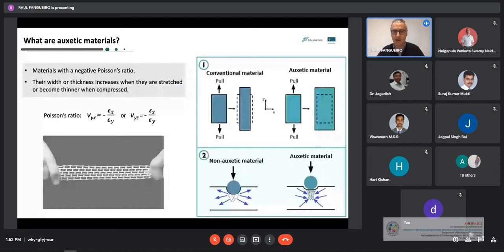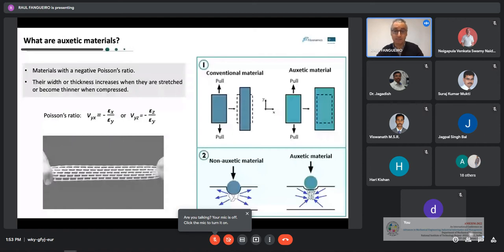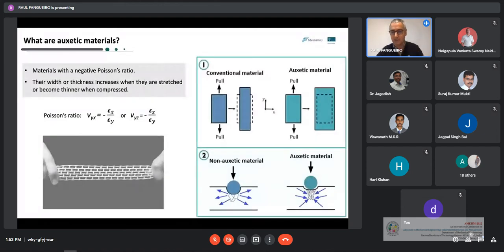It means that when we apply a longitudinal load, in opposition to a conventional material, in an auxetic material we also have expansion in the transversal direction. Or when applying an in-plane force or load, we may see that an auxetic material acts in a different way from a non-auxetic material, giving interesting properties to these materials. And as you've seen before, as we are working with fibers and fiber-based structures, we are able to build this characteristic into the material. And this is very important for several applications, because we can come up with very important characteristics of these auxetic fiber-based materials.